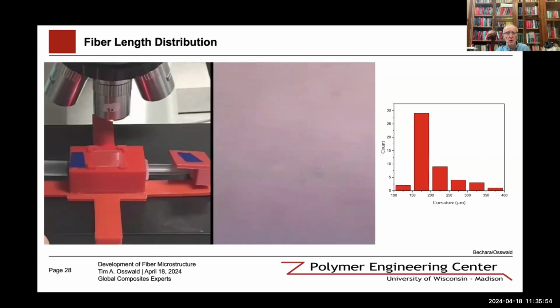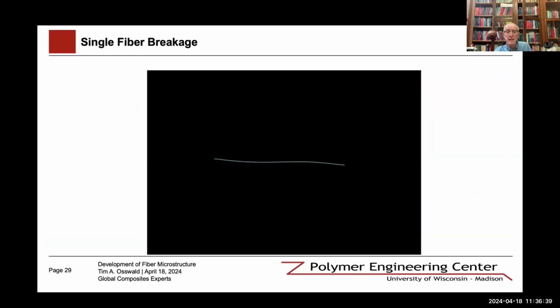There he recorded the radius of curvature, but he noticed that the radius of curvature varied from fiber to fiber. So there was a distribution of the radius of curvature, and the reason is that some fibers are damaged; they have a little scratch on the side, and that leads to variability. A perfect fiber that is nice and smooth can have a radius of curvature of 125 micrometers where it fails, but depending on the scratches, you could go to larger and larger radii of curvature. So we included that in the results.